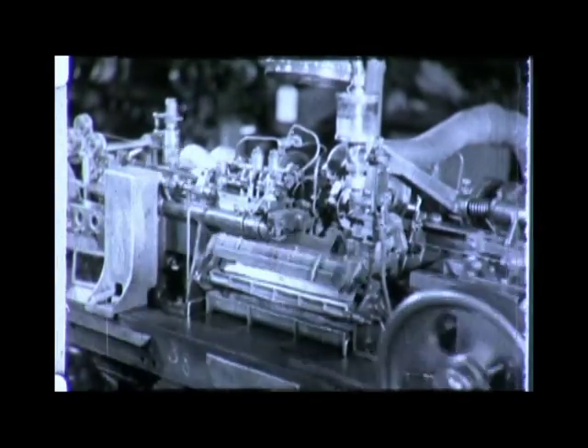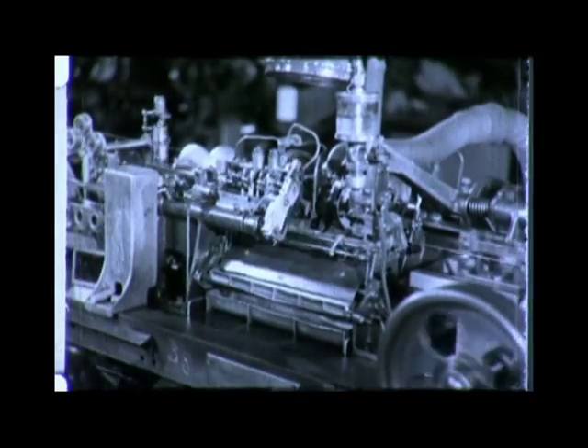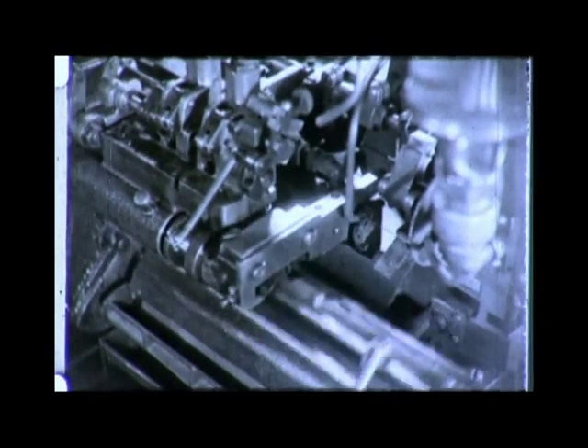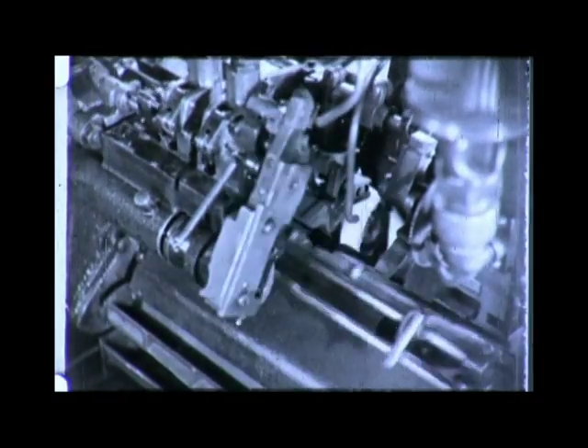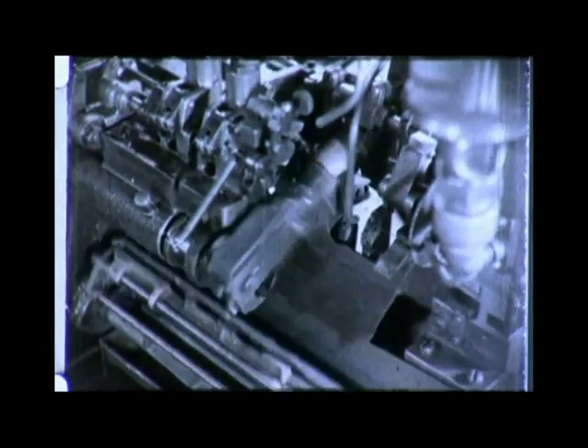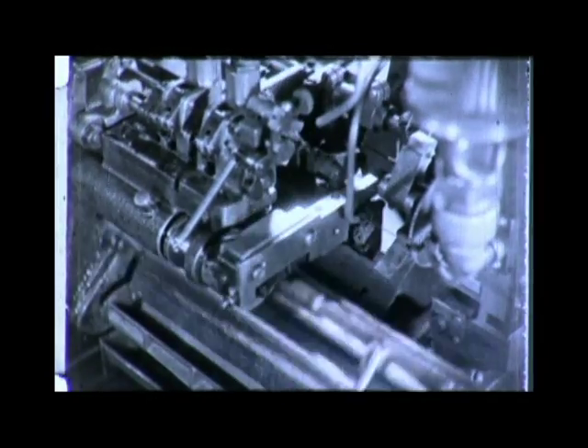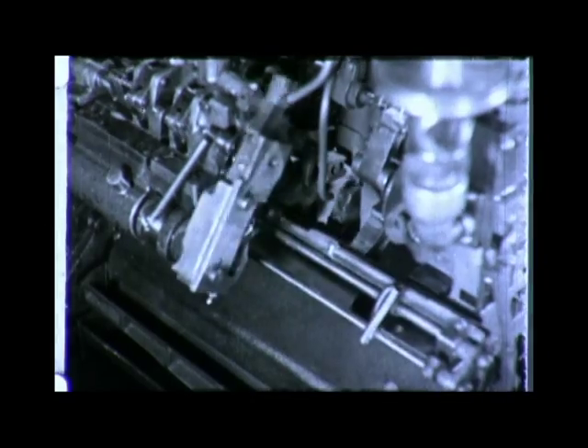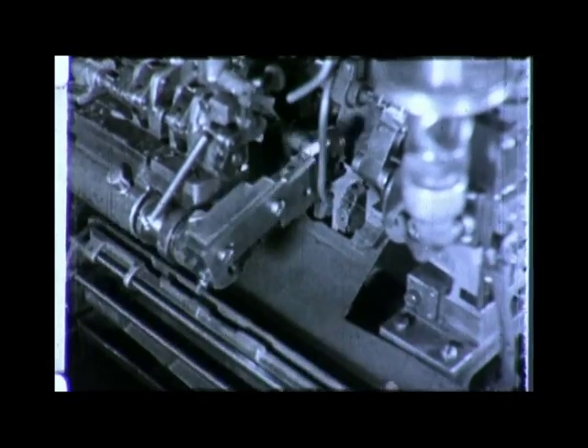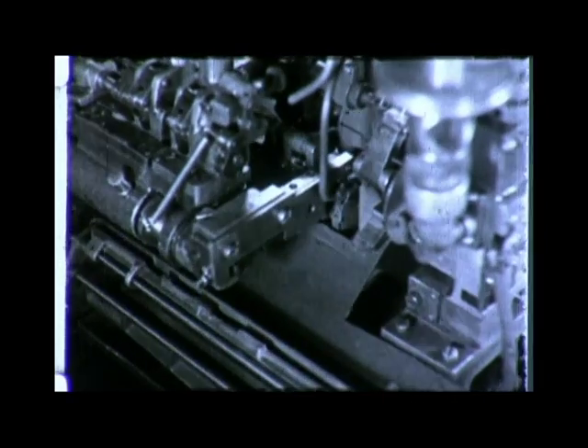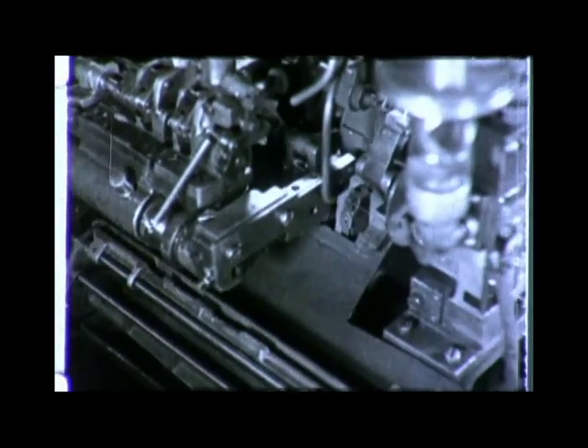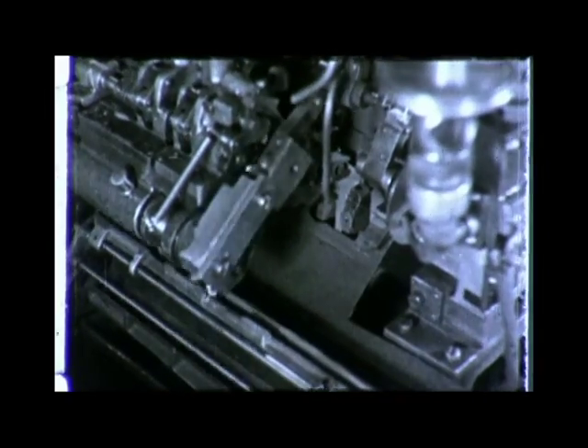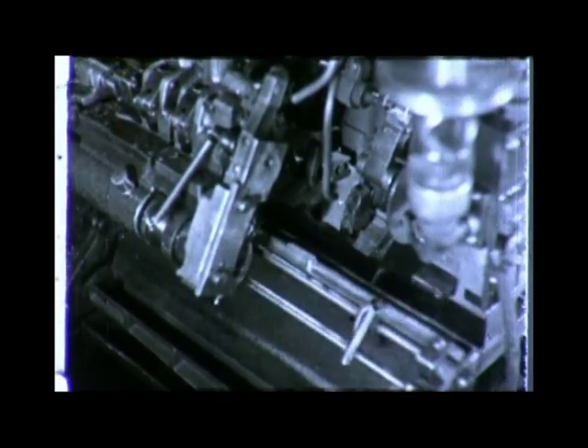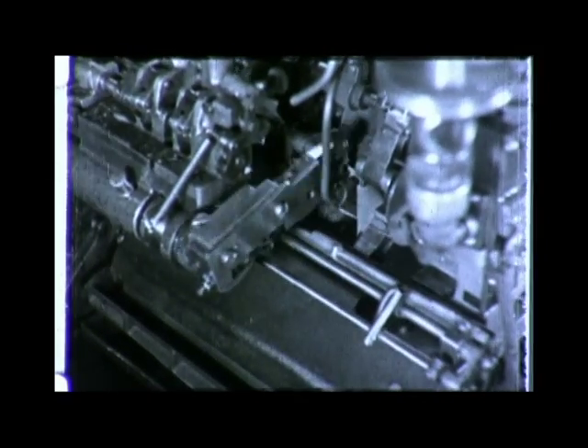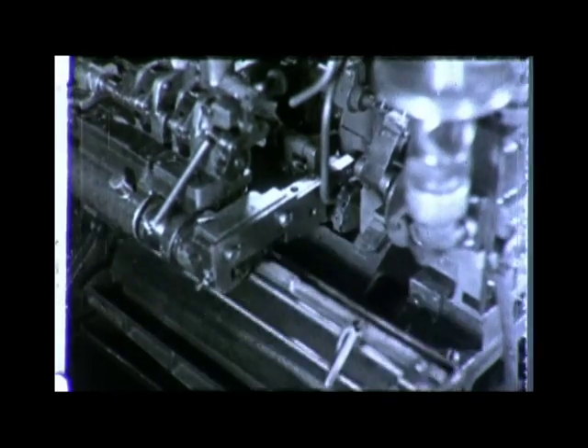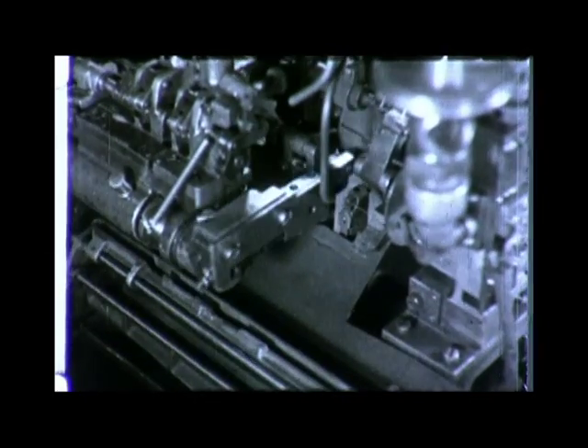This will give you a closer view of this lightning-like mechanism. Nickel wire on spools is fed into the machine from the left, and copper wire on spools from the right. You can see plainly there the action of the wire on the right as it rushes in to be welded to the other materials. The dumet is fed in from above, and every time the rocker arm swings down into position, a percussion weld is made, dumet to nickel and dumet to copper. As we slow the machine down, you can see the flash as the weld is consummated. You are observing one of the most intricate of operations in the manufacture of lamps.